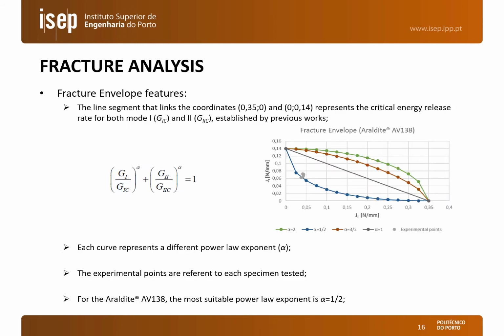Regarding the fracture envelope, this is a very important feature for the crack propagation analysis in structures, because we usually have mixed mode crack propagation. In this graphic we have 4 curves corresponding to 4 exponents in the power law mixed mode criterion, the parameter alpha, and we plotted here the different points for each adhesive of G1 and G2, and we can see that the most suitable exponent for this adhesive is undoubtedly the exponent of 0.5, which is on top of the values obtained experimentally.